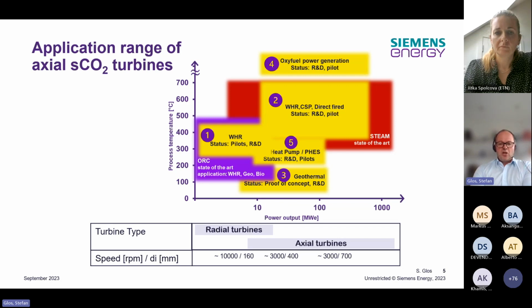And below that diagram, you see where we think that axial turbines can be used. So we think that starting roughly in an area of 10 megawatts, a reasonable axial design can be built. For the Cool Heat project, which I will show starting from the next slides, we were able to realize a very small axial turbine with a shaft diameter of roughly 160 millimeters running at 10,000 RPM. And if you scale that design up, you will reach somewhere between 30 and 50 megawatt the net frequency, so that you don't need a gearbox anymore, and then you have a diameter of roughly 400 millimeters.